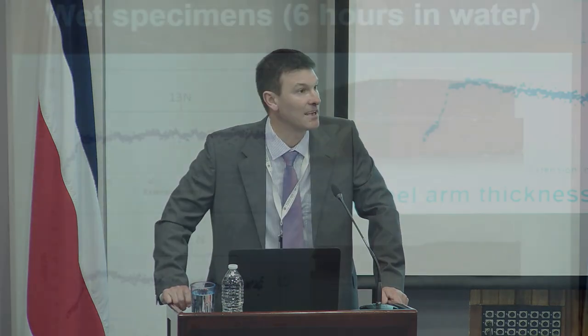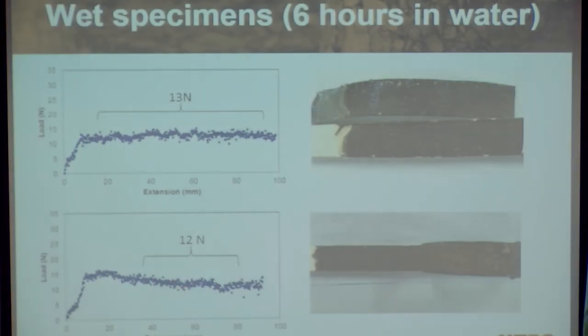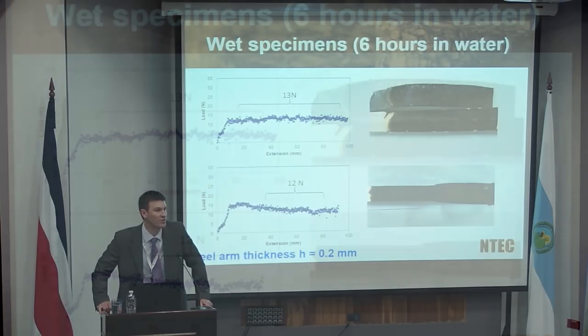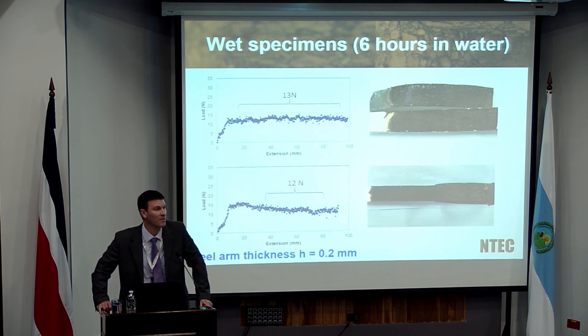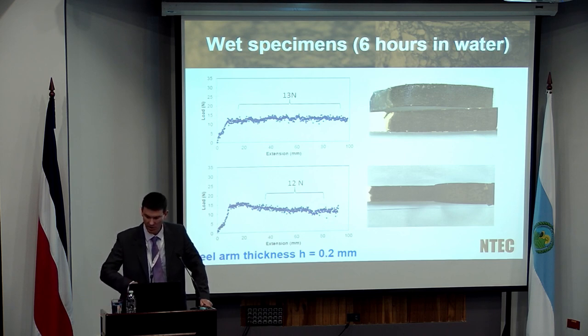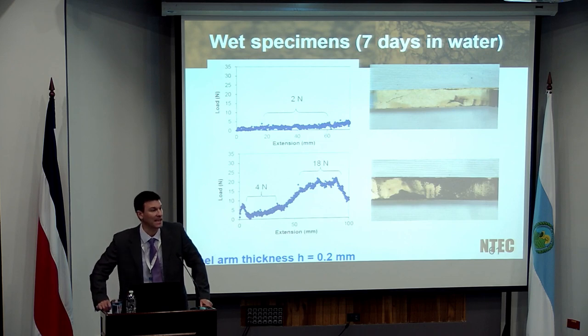If we look at the next set of figures, we've got it after 6 hours in the water bath, where we now see the reduction in that peel load has dropped from 30 down to about 12 newtons. So more than half the value after 6 hours. What is interesting, though, is that the failure mechanism hasn't changed. It's still primarily a cohesive failure. So what's happening is your bitumen effectively is losing strength rather than a change of the failure mechanism from the bitumen to the interface.